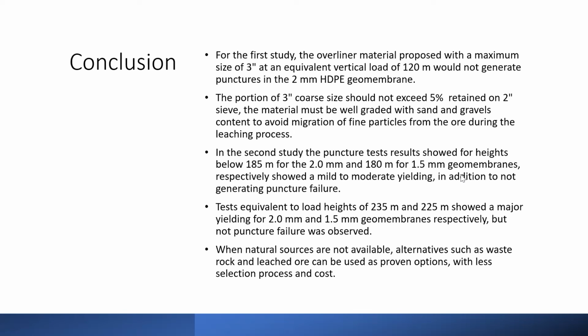In the second study, the puncture test results showed that for a height of 185 meters for 2 millimeters, and 180 meters for 1.5 millimeters, mild to moderate yielding was shown, and in addition it did not generate any puncture failure. And over 200 meters, major yielding was observed, but no puncture was observed in that case. I was actually surprised. And so basically we proved that it is possible to think about taking out the paradigm about the typical specifications we use for projects in terms of the overliner and protection to the geomembrane of the